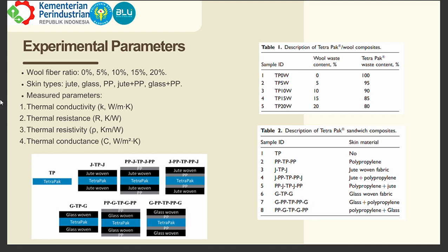These are the experimental parameters. The experimental parameters are summarized as follows. First is wool fiber ratios. They are using 0%, 5%, 10%, 15%, and 20%. The second is skin types. They are jute, glass, polypropylene, jute plus polypropylene, and glass plus polypropylene. For the measured parameters, they are measuring four parameters: thermal conductivity, thermal resistance, thermal resistivity, and thermal conductance. This measurement allows the evaluation of how fiber content and surface reinforcement affect the heat transfer.